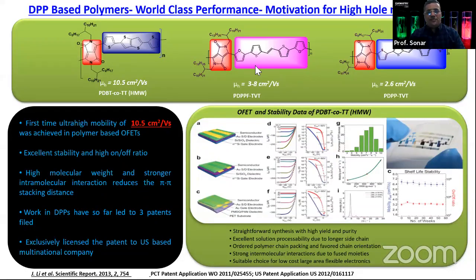Okay, so using some of these polymers, we can now push the mobility, in one case, to 10.5. We got the high molecular weight. And this is a Scientific Reports paper where we demonstrated this on flexible plastic, with all the stability studies. If you are keen, just look at that paper. But the main message is that we really can push this mobility value very high, and this has been patented successfully. We got some commercial benefit out of it, very glad.